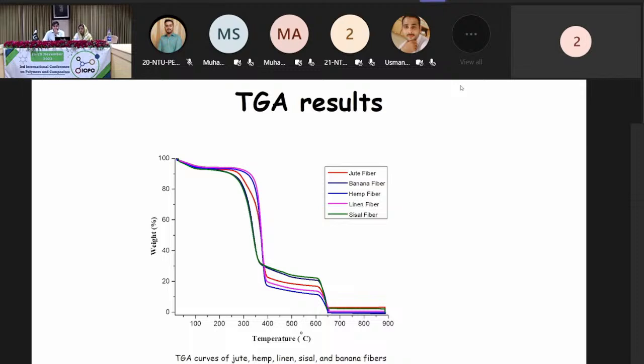The quantity of residual mass in the TGA curve abruptly drops between 148 and 416 degrees centigrade. Depending on the fiber type, the second stage, which involves the majority of weight loss, begins at 148 to 234 and ends at 395 to 416 degrees centigrade. This temperature range, where the rate of weight loss reaches its maximum value, is thought to be when hemicellulose and cellulose start to break down. The main weight loss occurs between 148 and 416 degrees centigrade.